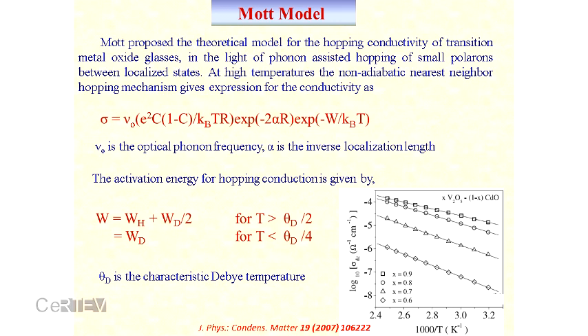In the high temperature range, what is high temperature? If the temperature is higher than half the Debye temperature, then it is called high temperature by definition. And if the temperature is less than one-fourth of the Debye temperature, it is called low. You can see the activation energy changes at high temperature. The activation energy consists of two parts, WH and WD. WH is called the hopping energy, with which electrons hop from one place to another. But due to disorder, surprisingly you can see one more term, the disorder energy.